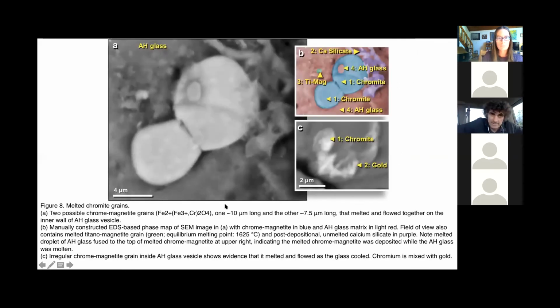Here is another piece of evidence. We have this Abu Hureyra glass, and we have the chromite grains. Usually you need very high temperature to get molten chromite grains. This is a chromite with iron, which means it's probably chromite magnetite grains, and you can see two of them next to each other. They were inside the vesicle, on the surface of the vesicle of the Abu Hureyra glass. When you look in detail, some of the chromite grains were associated with gold. So we found chromite with gold association, again on the surface of these vesicles on this glass material.